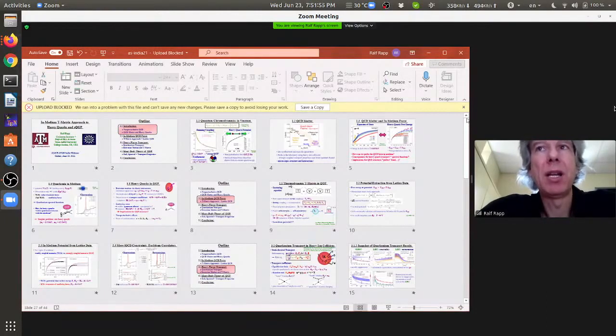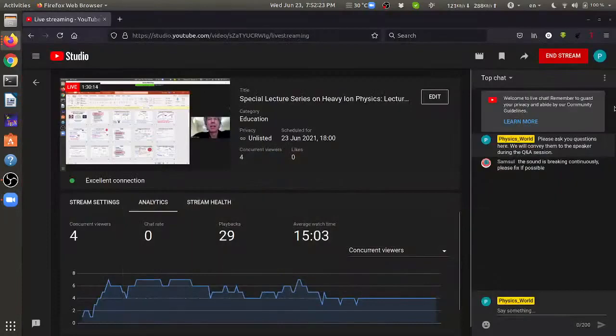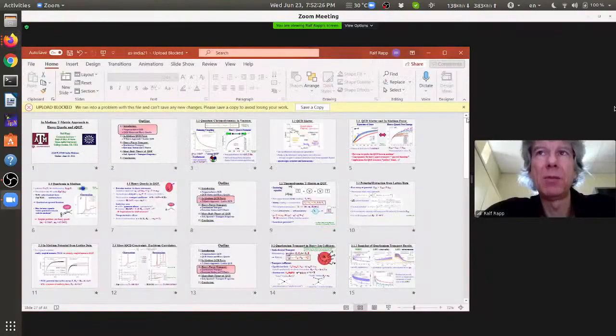I was very encouraged by those results, because personally I think if the free energy would be the potential, it would mean the imaginary parts are small. The potential is rather weak, and I think there's no chance to come up with a strongly coupled QGP if you would use that as your input interaction. So I was very encouraged by quite a number of lattice studies, both in terms of correlation functions, but also in terms of extracting real and imaginary parts of the potential. That now I think really is going in the direction of very large imaginary parts and real parts which are well above the free energy.